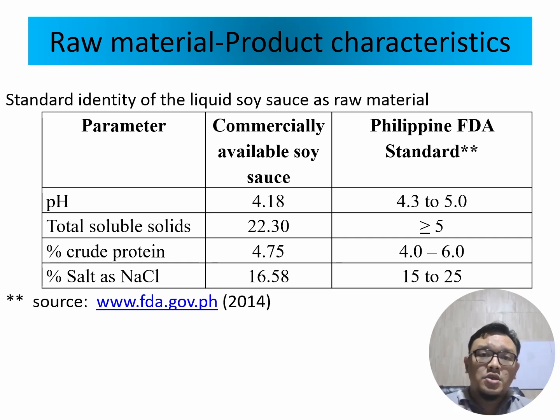For the raw material, since we used commercially available soy sauce for this study, we had to evaluate its quality to see if it complies with the Philippine standard for soy sauce. There are certain parameters established in the Philippine standard for soy sauce: pH, total soluble solids, percent crude protein, and percent salt content. We evaluated the commercially available sample, and some of its parameters comply with the Philippine standard, with slight variances in pH, but the protein, the salt content, and the TSS are compliant with the FDA guidelines.